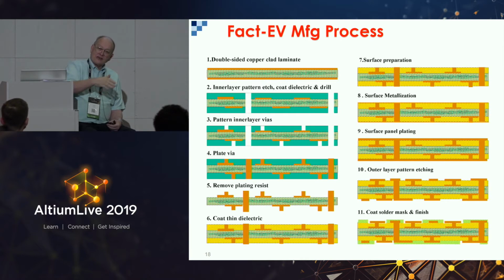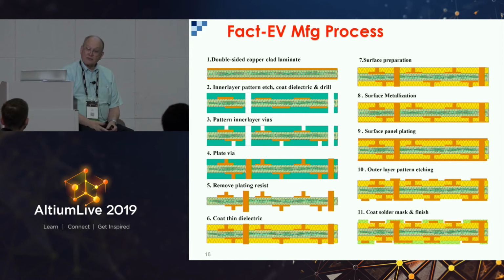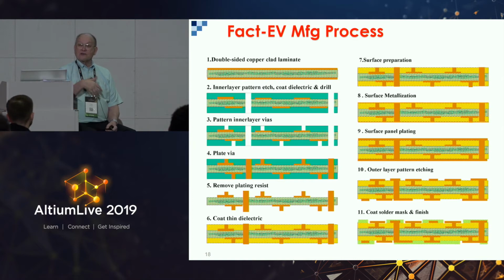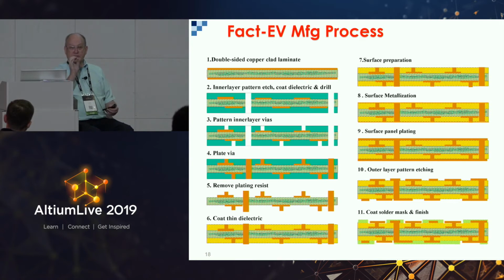Now, one of the reasons they use a liquid dielectric is so they can use liquid crystal polymer, LCP. LCP is a terrific low-loss material. And it's one of the secrets of how you get to 5G, to use a liquid crystal polymer, because it's got 0.00018 dielectric loss. So it's as good as Teflon without being as tough to work with as Teflon is, and it's a liquid. So you roller coat it or flow coat it or spin it onto your dielectric as per the semiconductor, and then cure it, and then you metallize it. And you have a way of precisely controlling the dielectric properties and thicknesses. And so it's called FACT EV.